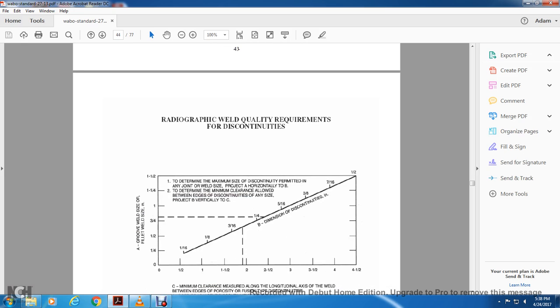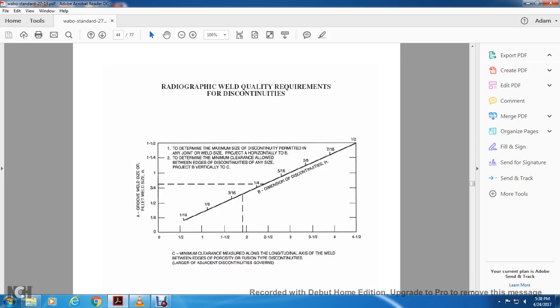Radiographic welding quality requirements for discontinuity. C equals the minimum clearance measured along the longitudinal axis between the edge of the porosity or fusion type discontinuities. Larger adjacent discontinuities govern. A is the groove weld size or fillet weld size in inches. 1. Determine the maximum size of the discontinuity permitted with any of the joint weld size, projection horizontal to B. 2. Determine the minimum clearance allowed between the edge and the discontinuity on any side of the projection B